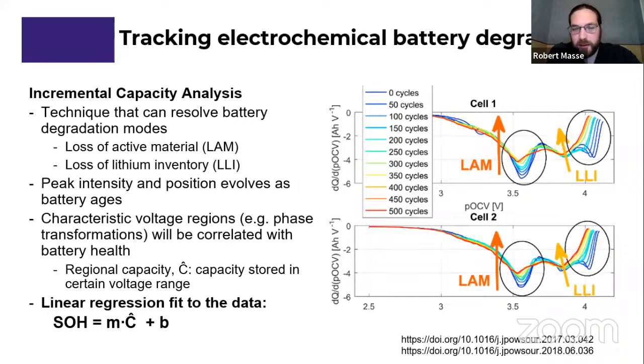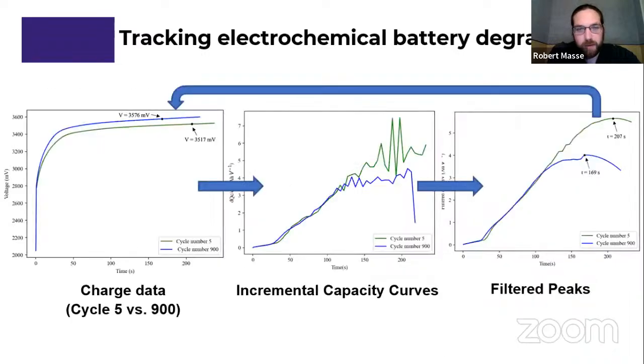So these peaks are going to evolve over time as the cycling. The intensity and position is going to change with time as the internal resistance of the battery changes, and as you lose active lithium in the battery. Those types of different side reactions are consuming your active material, and you can basically use this as a quick and dirty estimate of the state of health, using just a quick linear regression.